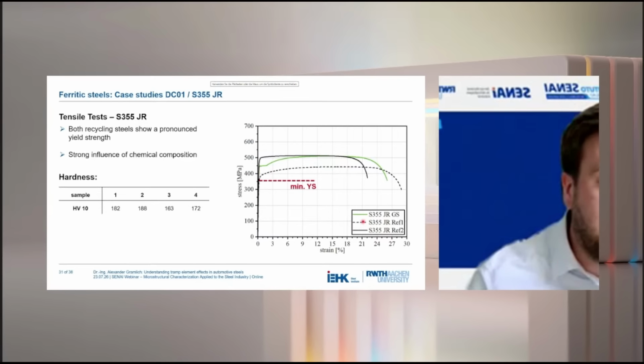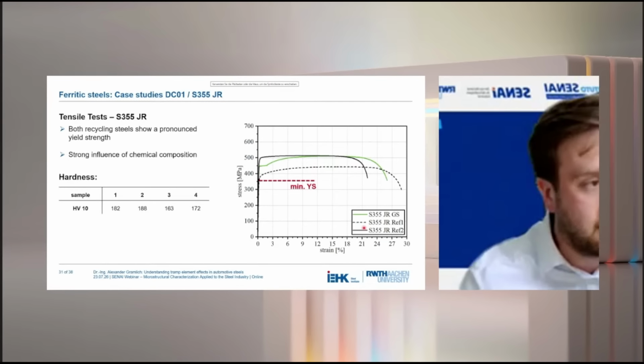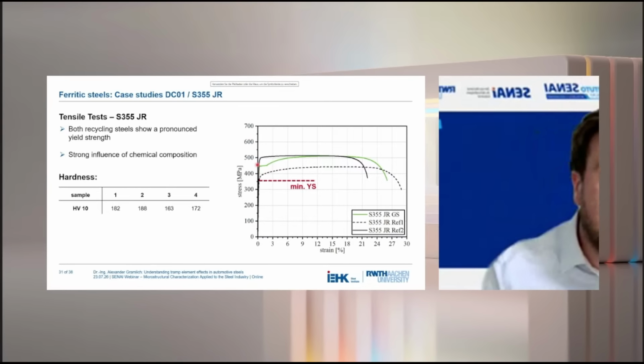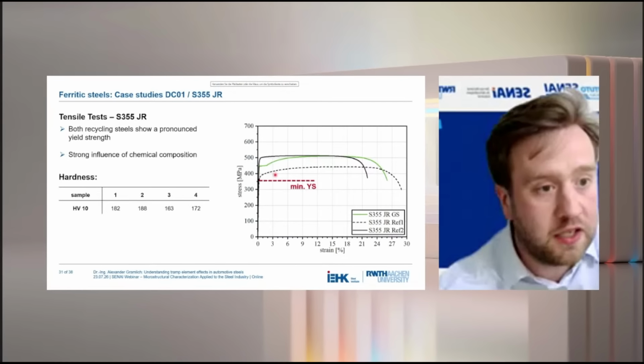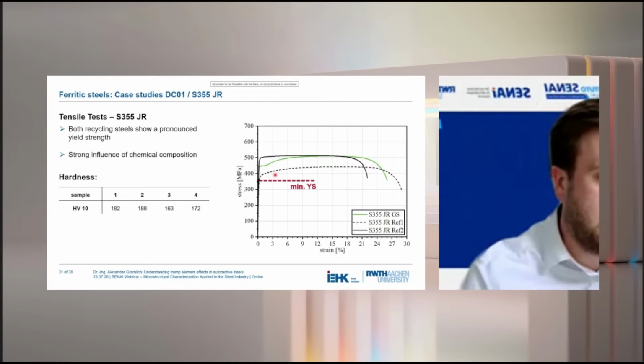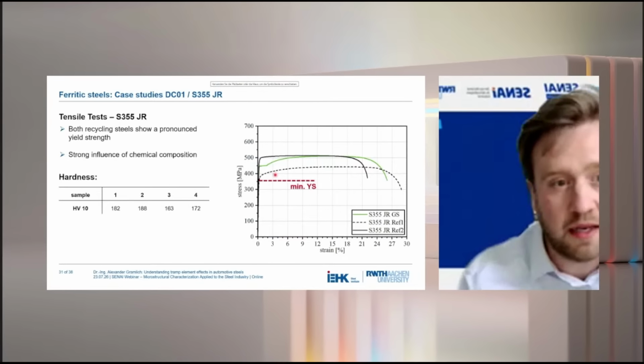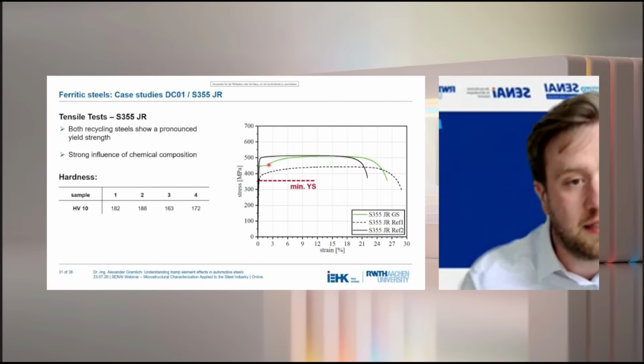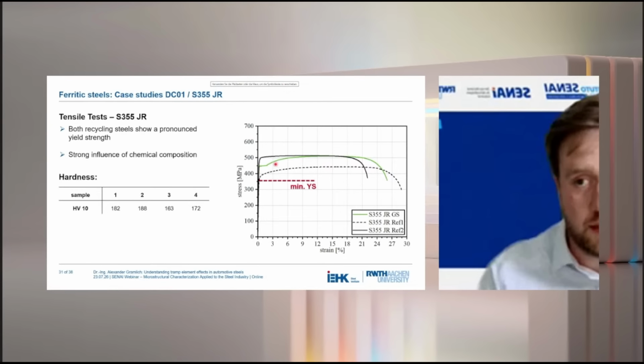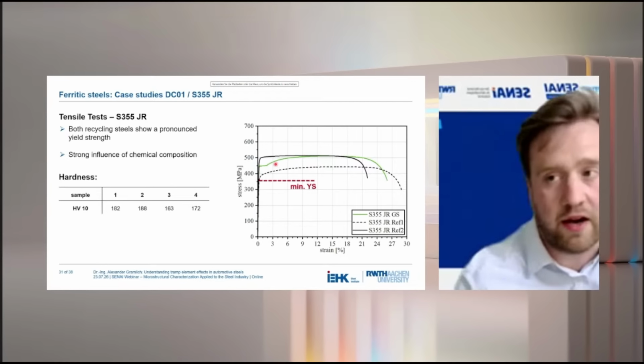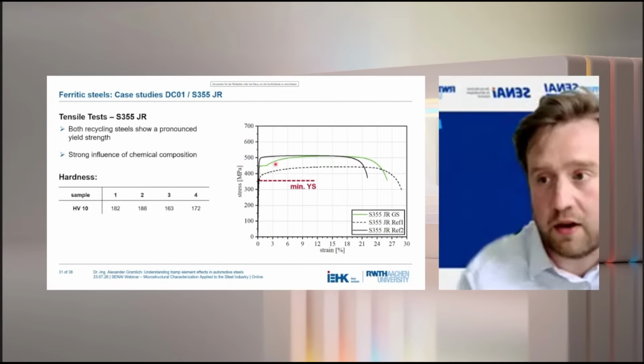We had three different alloys here, two variants of S355 with slightly different carbon and manganese concentrations, and our reference steel somewhere in the middle. And what I want to point out here is not really strength and ductility, because this changes very much, of course, with the carbon and the manganese concentrations. But what you can see is that we have a pronounced yielding here in this steel. So this is connected also to higher nitrogen concentrations, which I pointed out in the beginning of the talk.